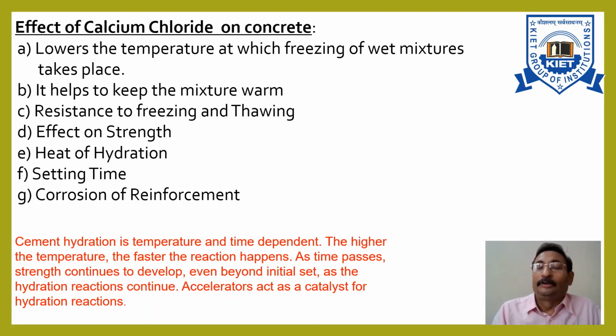It affects the strength. It changes the heat of hydration. It affects the setting time of the concrete. An excessive amount of calcium chloride in the concrete mix may result in rapid stiffening or an increase in drying shrinkage.